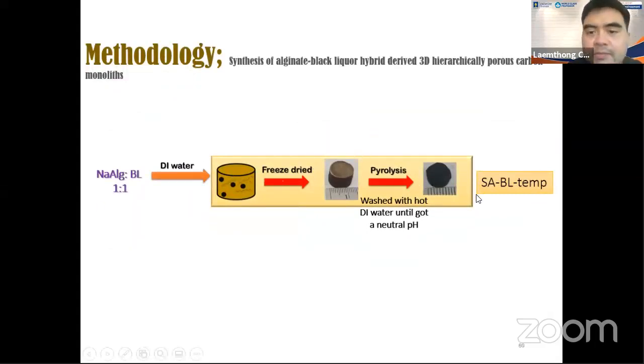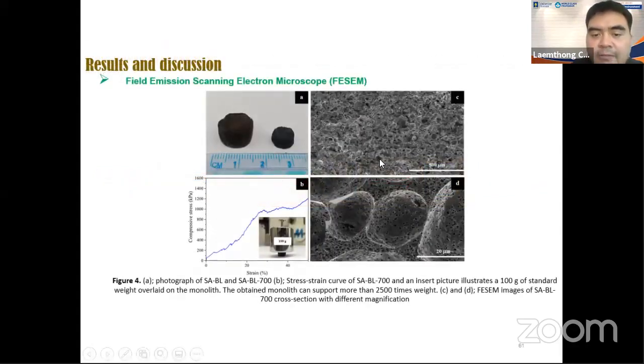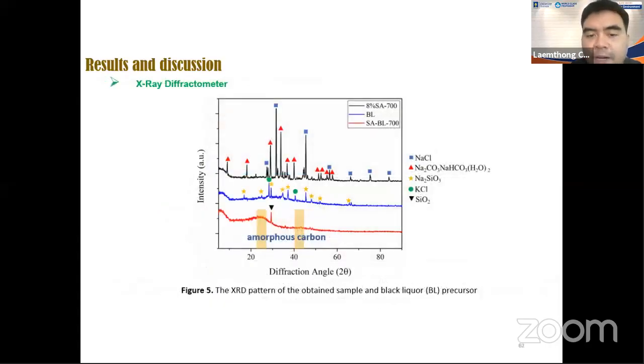And so we have the synthesis protocol like this. We freeze dry, and then afterward we burn it in the oven, and then you have quite nice hierarchical porosity. That means it contains both macropores and mesopores, and also an abundance of microporosity. We use this to adsorb lead ions because we have a lot of microporosity, which is suitable for small molecules or small pollutants like ions.